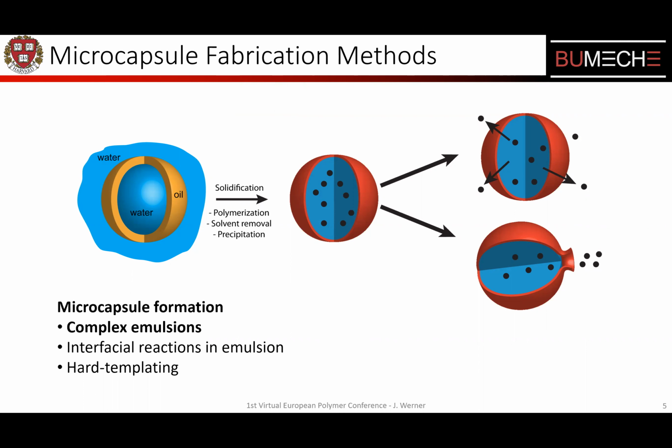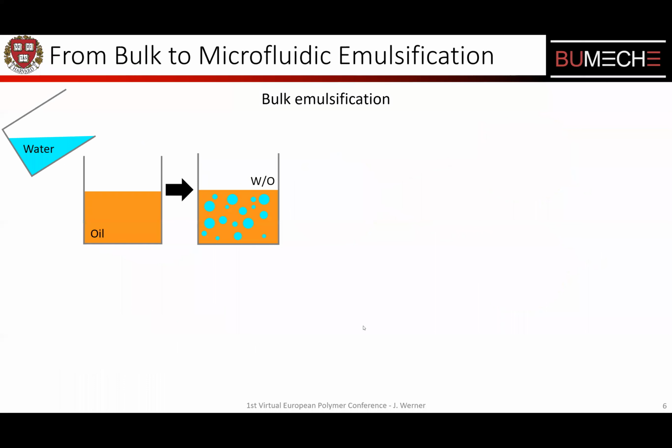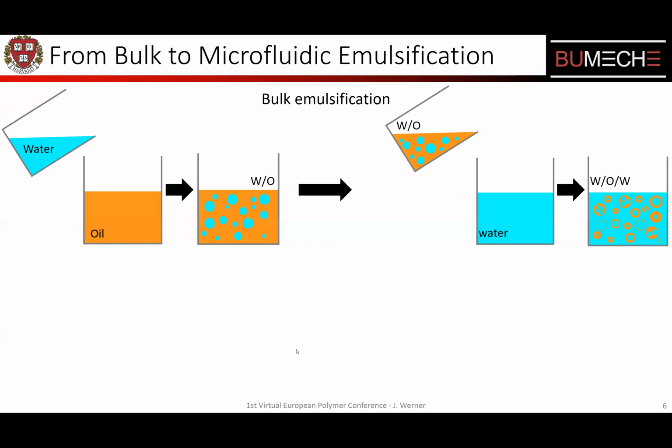the respective monomers present. Now, a bulk way of making emulsions, of course, is homogenization or high shear emulsification, just simply mixing water with oil to get what we call here these water-in-oil emulsions. But for complex drops that I discussed, such as double emulsions, one would need to take these pre-emulsions and emulsify them a second time. That's how it is typically done to obtain these water cores inside oil shells.